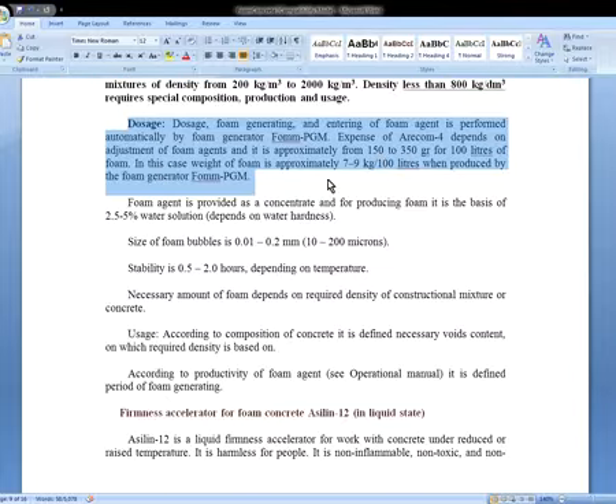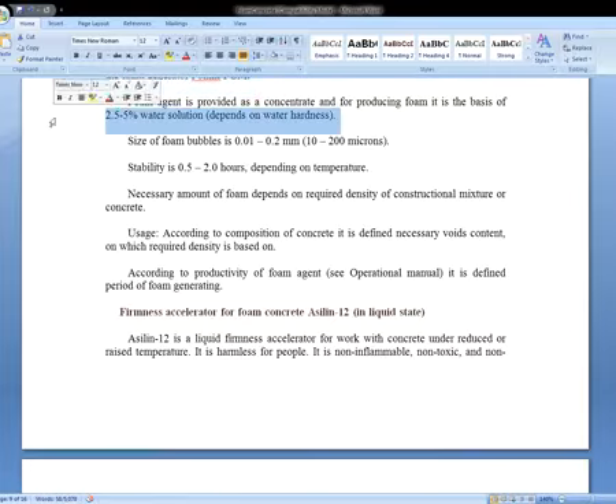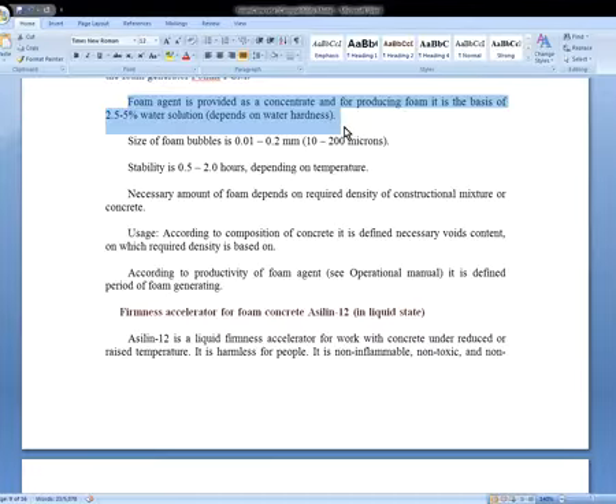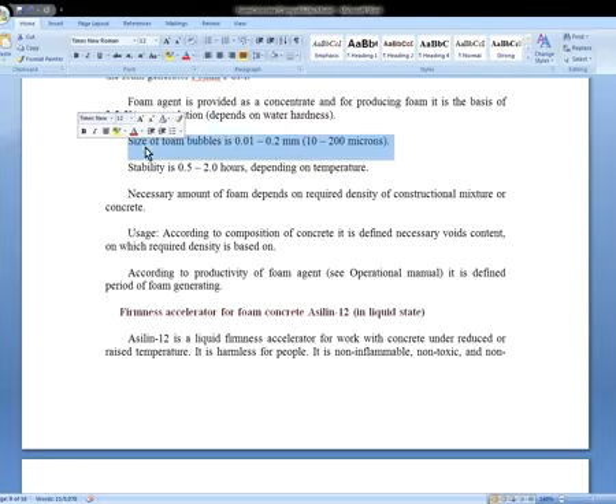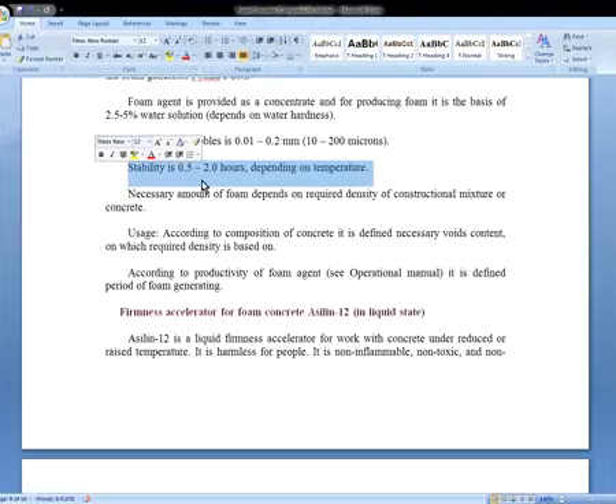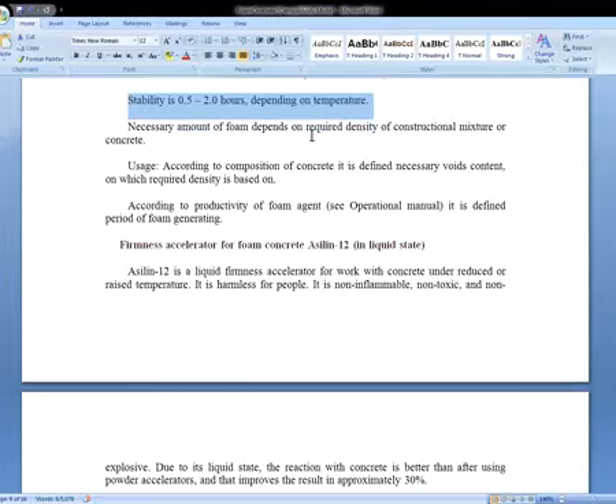In this case, the weight of foam is approximately 7 to 9 kg per 100 liters when produced by the foam generator Fomm-PGM. Now, foam agent is provided as a concentrate, and for producing foam, a 2.5 to 5% water solution is used, depending on water hardness. The size of a foam bubble is 0.01 to 0.2 millimeter. You can say bubbles are very small, in microns 10 to 200, so you will find not very big bubbles in that, small bubbles. The stability is 0.5 to 2 hours depending on temperature.